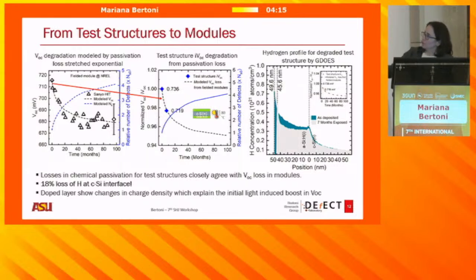You may be asking what's going on here. Why is there a shift? I think that has to do with the homogeneity of our deposition, since these are not exactly the same samples. So the main observation here is that we actually see about 18% loss of hydrogen at the crystalline silicon amorphous silicon interface.